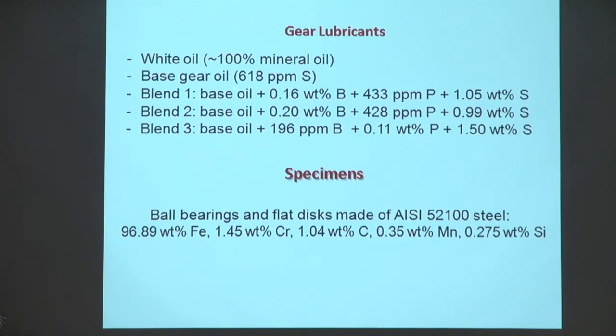Blends 1, 2, and 3 are the base oil to which we incorporate a new material, boron, with reduced levels of phosphorus compared to the zinc dialkyl dithiophosphate. So this represents contents of zinc dialkyl dithiophosphate. You can see much higher sulfur and much higher phosphorus here. So here we are reducing the phosphorus to this level or this level. From weight percent, I'm going to parts per million, a reduction in phosphorus, and a reduction in sulfur also, by adding another element that is not producing environmental effects, boron.